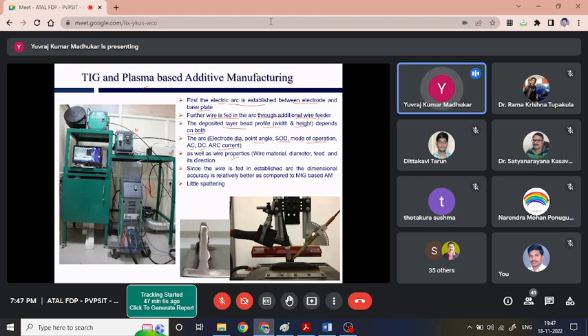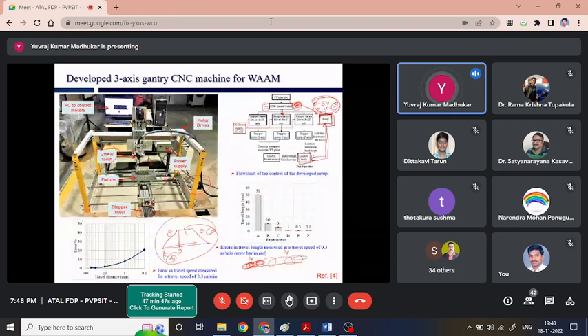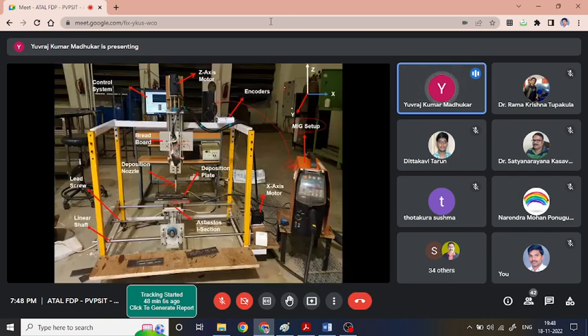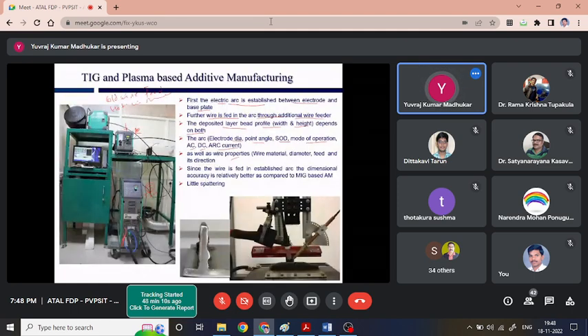Now, if we go to the market, different kinds of wire feeders are available. Some of them are typically called a cold wire feeder. There are some hot wire feeders also available. So we can buy any wire feeder, no problem at all. However, one thing we have to ensure when buying the wire feeder is that it can be triggered or communicated with through some additional circuitry or some relay, so that we can connect this wire feeder like we connected this GMAW power source. Similarly, the wire feeder can also be connected to the relay, and as soon as the arc has been established and is stable, the wire feeder should start feeding the wire. So we have to ensure that particular provision is always there in a wire feeder.